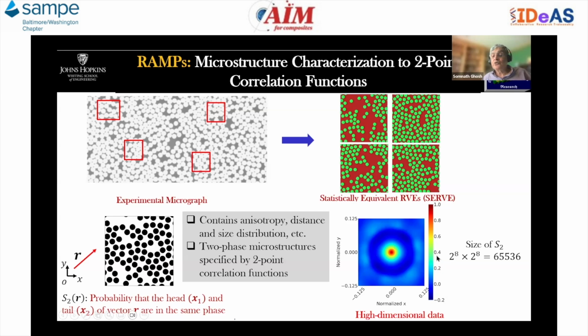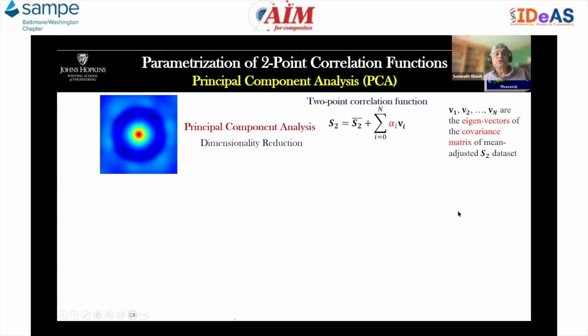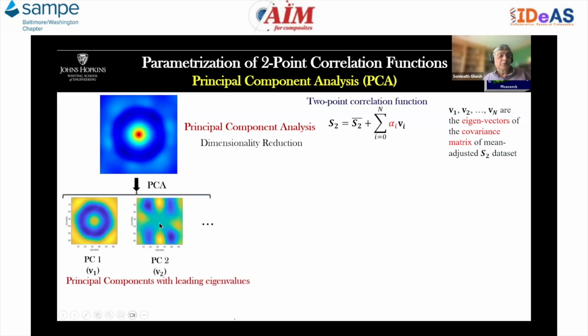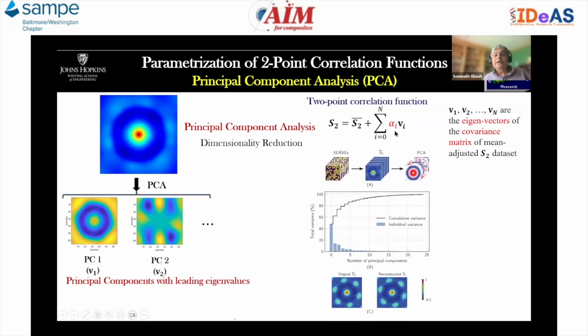But these 2-point correlation functions generally correspond to high-dimensional data. So to reduce that, we do principal component analysis, where you can see it's basically reducing this high-dimensional space into a space that corresponds to the eigenvectors of the covariance matrix, these are the V's, together with the alphas which correspond to the principal components. These are the principal components of that analysis with the leading eigenvalues. And we take only a certain number of these principal components.